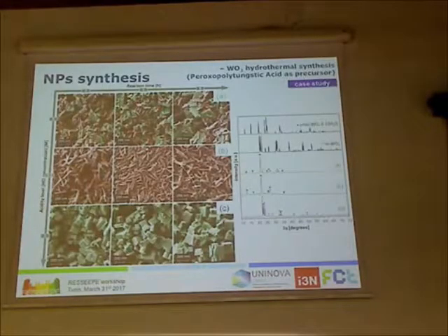So that's what we did in the lab. We try to synthesize the particles using a technique called hydrothermal synthesis. Basically, you put inside a kind of autoclave the precursor for the material that you want to create. You heat, you create a lot of pressure inside, high temperature, and you start to precipitate these particles that start to grow in these directions. So depending on the processing conditions, we can tune conditions to get these kind of particles we want, so these kind of rods.